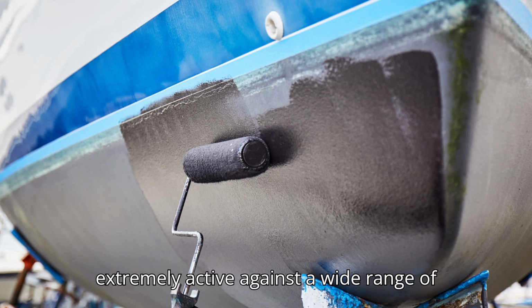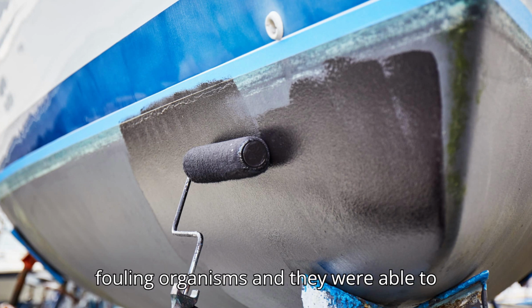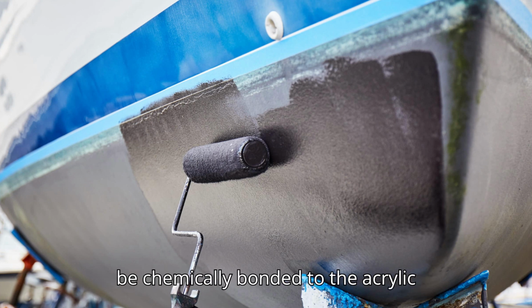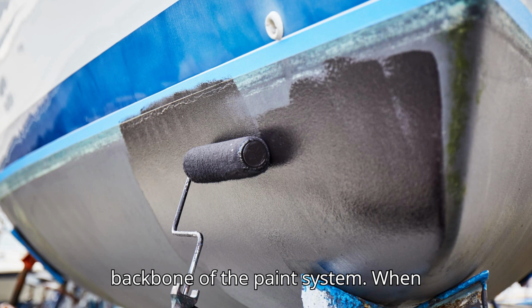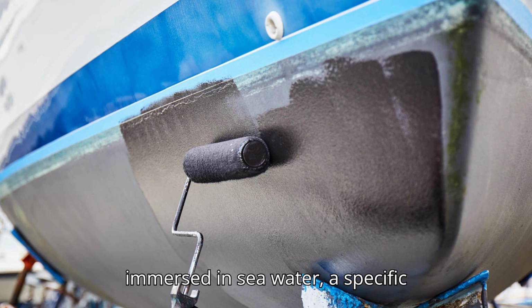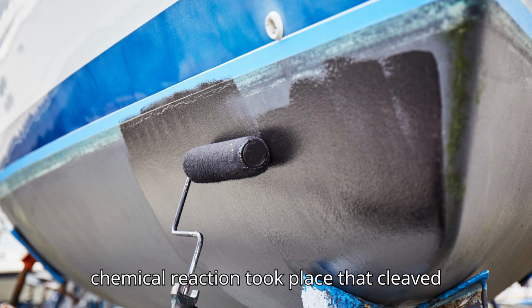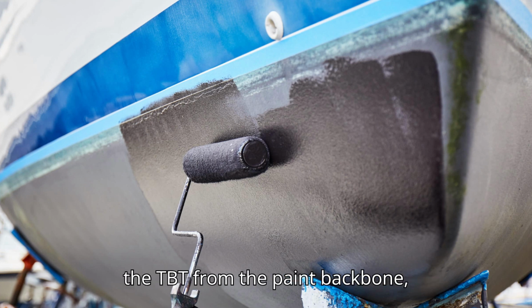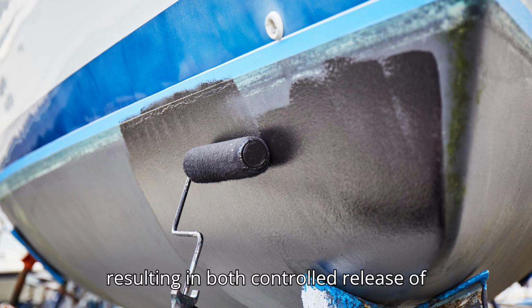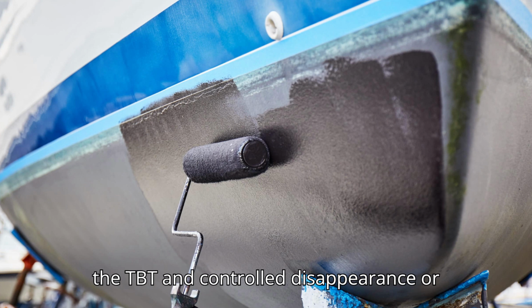TBTs were extremely active against a wide range of fouling organisms, and they were able to be chemically bonded to the acrylic backbone of the paint system. When immersed in sea water, a specific chemical reaction took place that cleaved the TBT from the paint backbone, resulting in both controlled release of the TBT and controlled disappearance or polishing of the paint film.